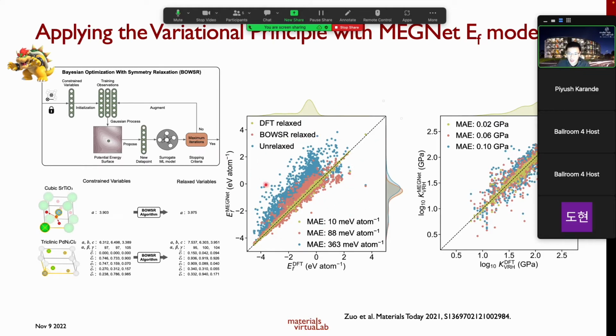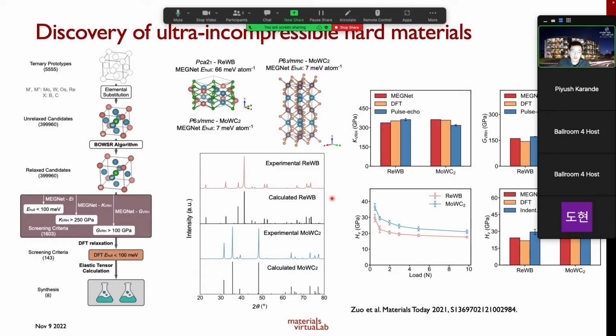And we can actually show that this kind of Bayesian optimization process can significantly improve the machine learning property predictions, and then we can use those predictions to actually do material screening, right? So just to show you an example of a success story, there's this work that we performed where we tried to look for ultra incompressible hard materials. We started from about 5,500 structure prototypes. We do various substitutions to get about 400,000 candidate structures. This is a very large number of structures which you can't actually do just pure DFT screening on.